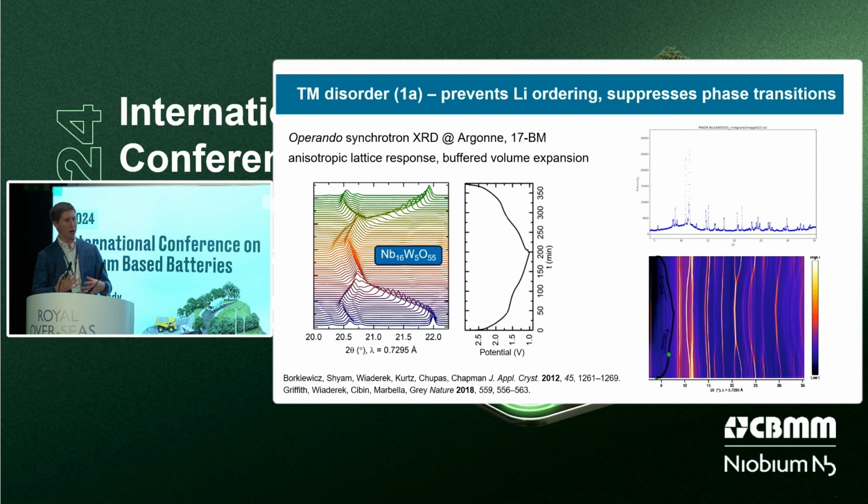And so most battery materials that started off in a stable phase, where either everything would expand or everything would contract, would undergo a bigger volume change per unit of lithium that you put in. Here, we're putting in 1.5 lithium per transition metal up to 2 lithium per transition metal, and we're still staying in the order of 5 to 8 or 9% volume expansion, which is less than graphite. So they're not zero expansion like LTO, but LTO is only doing half an electron. So it's an interesting mechanism for stabilizing the structure, even in these large particles.